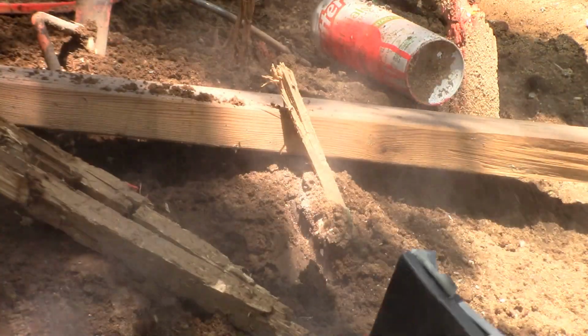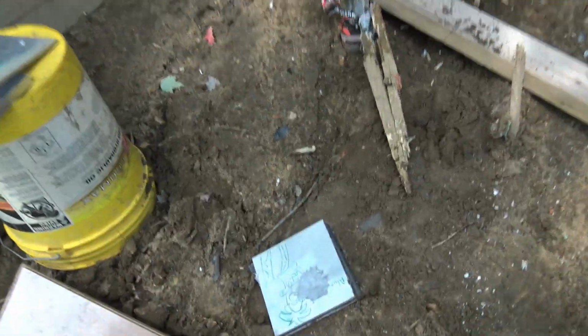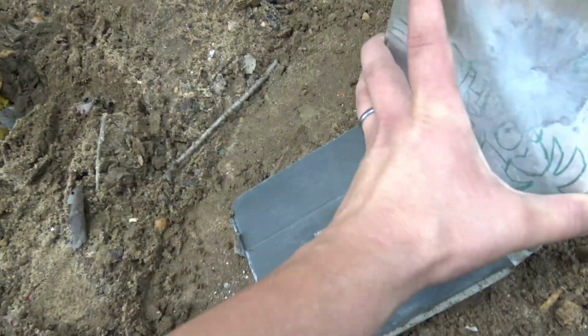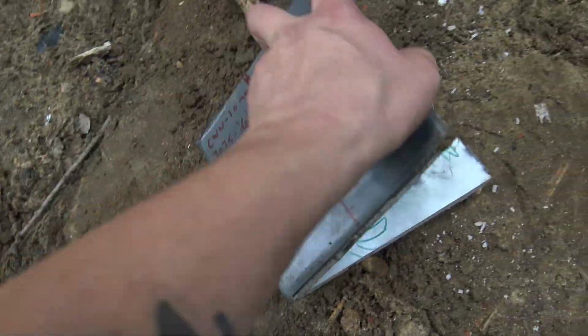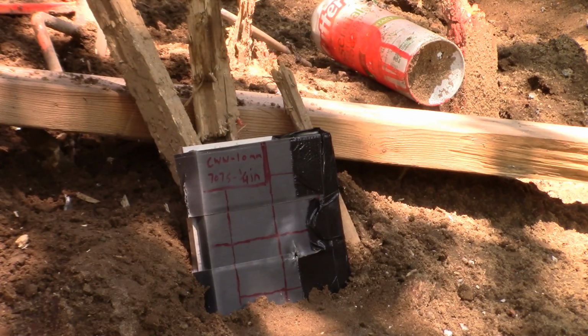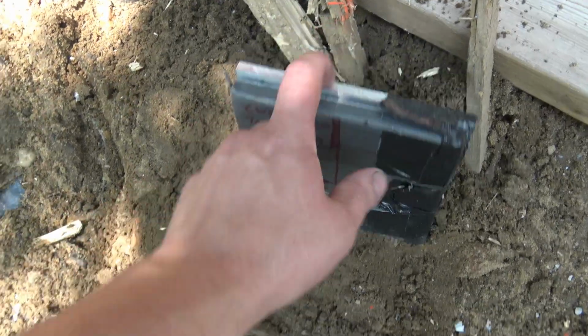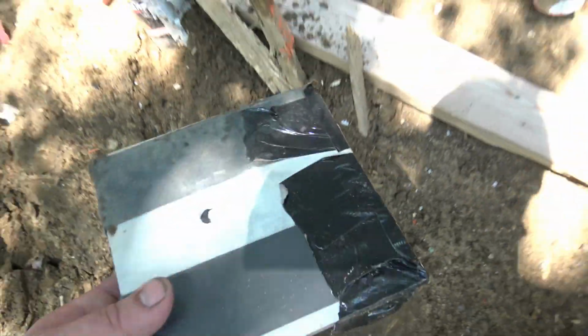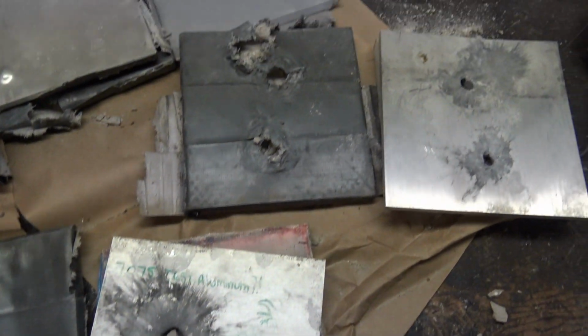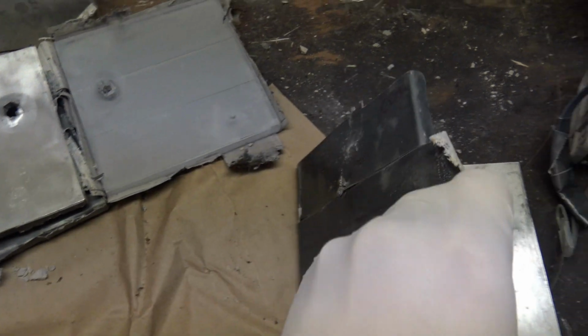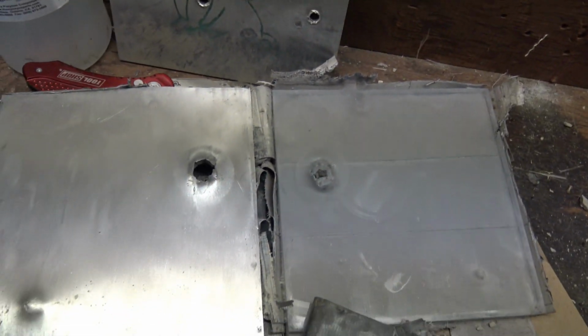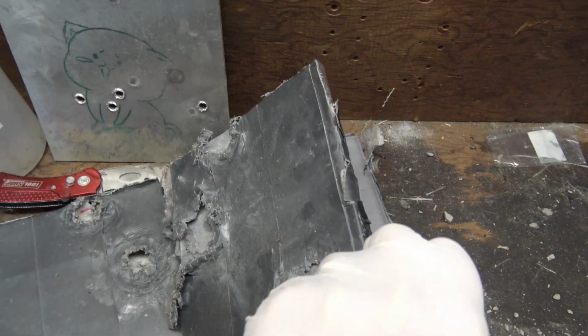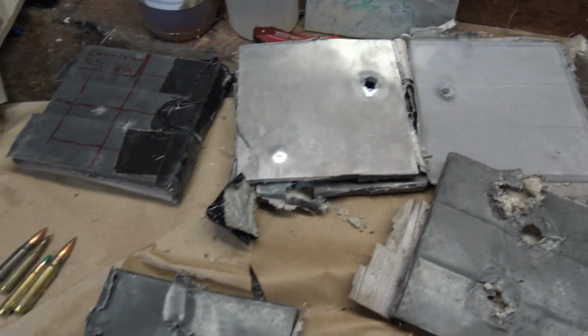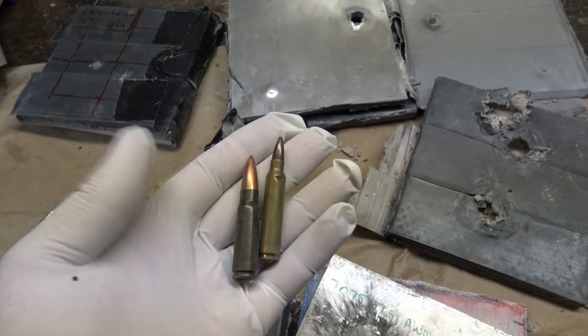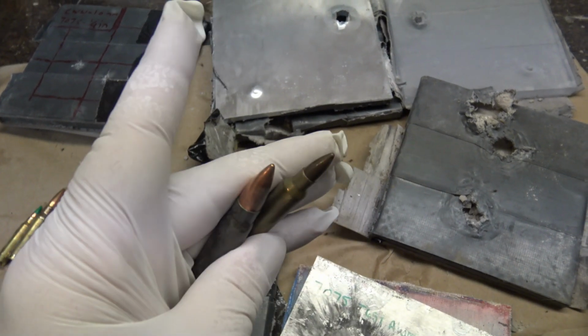I then moved on to the one with a porcelain strike face and 7075 backing it, and we finally saw the 55 grain 5.56 stopped. However, the M855, also known as the green tipped 5.56 mild steel core, did make it through. Now I'm going to show the next 3 plates together because they were so similar in design, and they gave very similar results. Really, the only difference between Turtles, Arctics, and the polycarbonate plate was the backer. For these 3, plus the last one I just showed, I've drawn quite a few different conclusions.